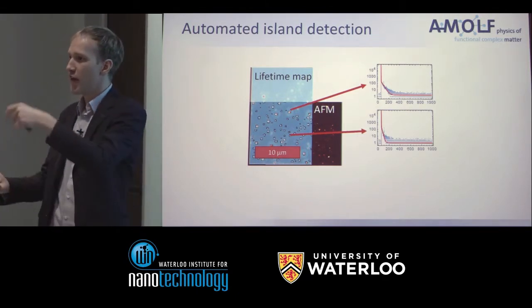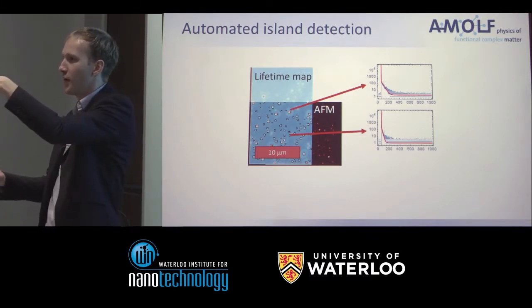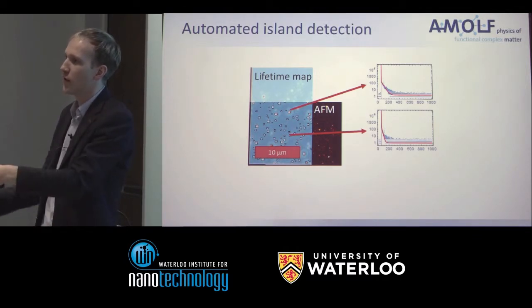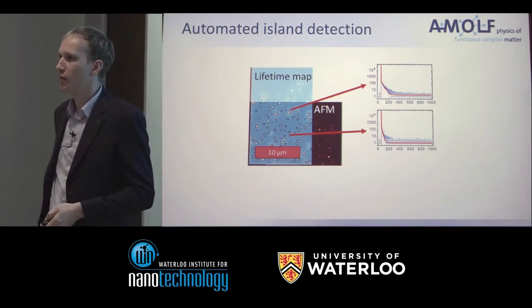And what we're looking for is a change in the delayed lifetime. So if the delayed lifetime gets faster, that means that these triplet excitons that have been here are somehow gone earlier before they emit a photon. And so they somehow have to be quenched. And that could be via a transfer into silicon. So before they go back to the singlet and emit, they transfer into silicon. And that's why the delayed lifetime gets faster.